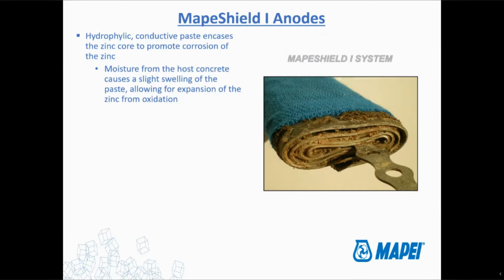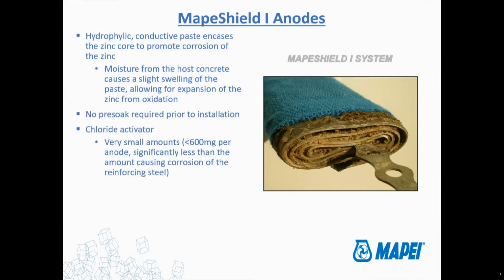The MAPEI anodes use just a big zinc plate folded on itself like you see here. Then there's a hydrophilic, conductive paste that is placed around the exterior of the plate. As the hydrophilic paste comes in contact with the water and, say, the patching mortar that you're pouring around it, it starts to expand just a little bit, which leaves room for the formation of those zinc oxides that are going to form when the corrosion starts happening. So you don't get the cracking from expansion of the anode like you would with cracking of the reinforcement steel.